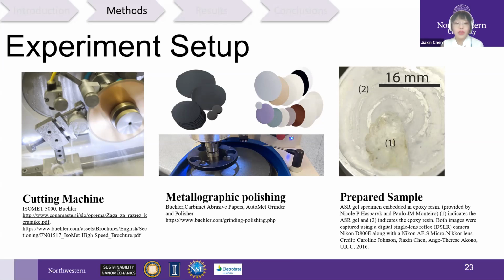In order to have a uniformly flat and smooth surface with a low roughness, we applied a metallographic polishing step. The objective of this step is to increase the accuracy of small-scale mechanical testing. The rule of thumb created by Miller et al. in 2008 is to have a surface roughness less than 1/5 of the maximum penetration depth. Before preparing our sample, to support it, we embedded our sample in epoxy resin, whose material properties are known.